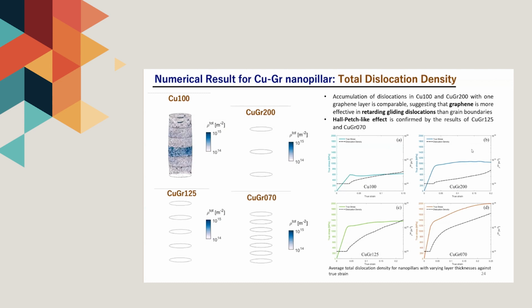The accumulation of total dislocations is depicted in black dashed lines. In contrast with the copper 100, the high accumulation of total dislocation density in the samples for copper graphene 125 and copper graphene 070 shows the Hall-Petch-like effect as a result of the number of graphene layers.